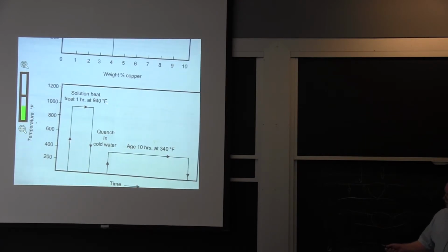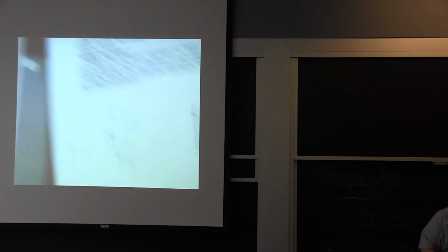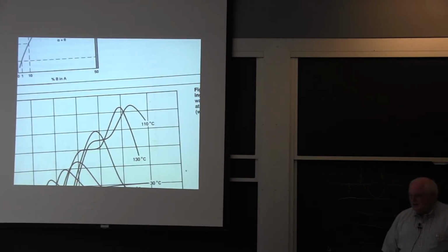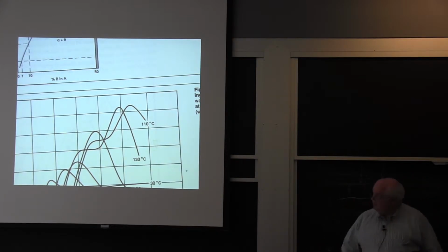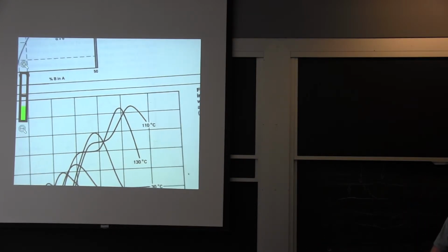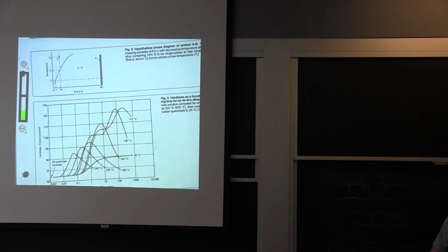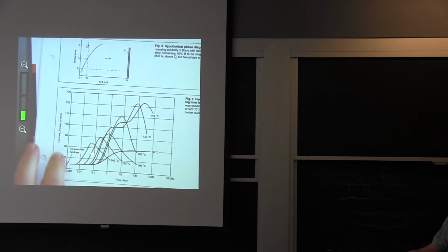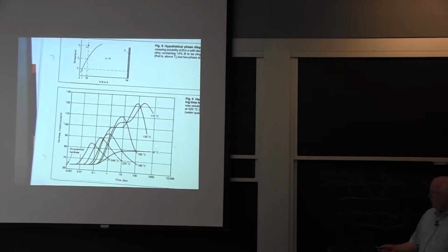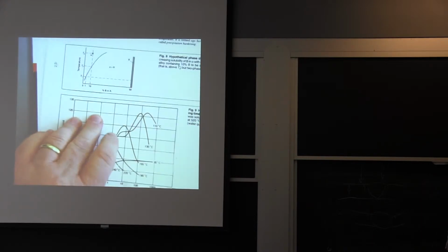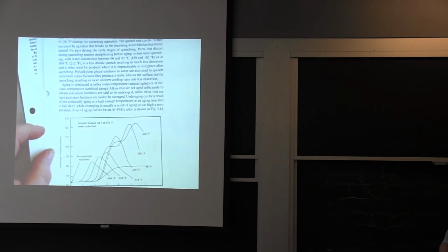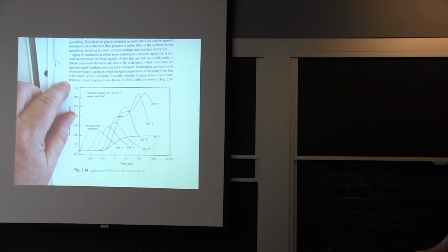In fact, they quench in cold water, so the solution heat is for 1 hour at 940. They age for 10 hours at 340 degrees Fahrenheit. And they increase the strength. They can double the strength. Okay? And the doubling in strength looks like this, depending on the temperature. This is centigrade, but I have another one. I'll put up the other one that's in Fahrenheit since we just had Fahrenheit. Same curves. Just someone likes to use Fahrenheit.